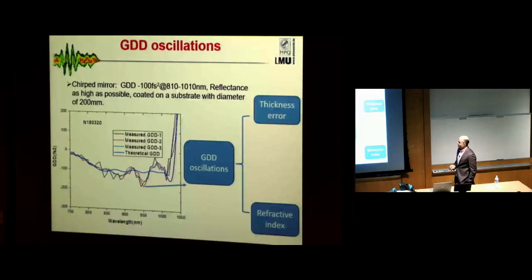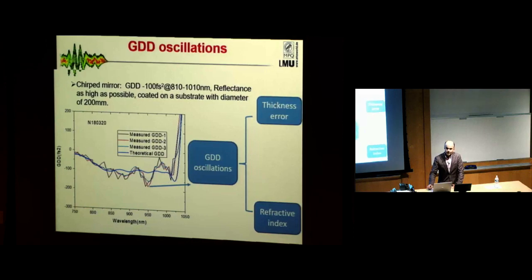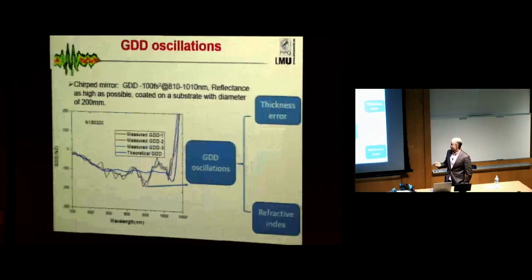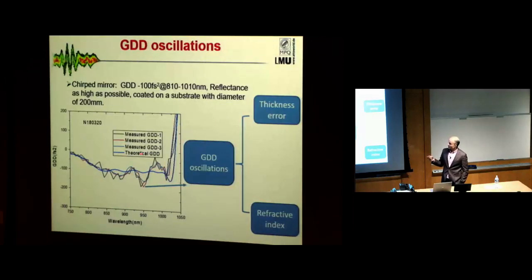When we produce a structure and measure the group delay dispersion, which is the second derivative of phase properties, we measure a few samples from the chamber. We see that our curve does not look like the theoretical curve, which looks like the blue curve. It has some oscillation, and actually there are two reasons for this oscillation. The layers which we produce should have a certain optical thickness. Optical thickness is the refractive index multiplied by the physical thickness. It means the reason for this oscillation might be errors in physical thickness or some change in refractive index.